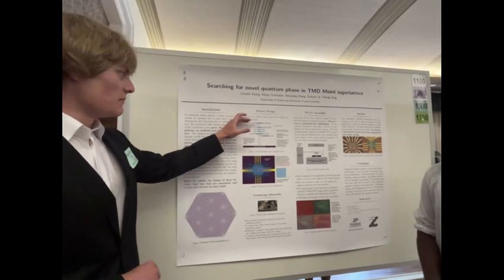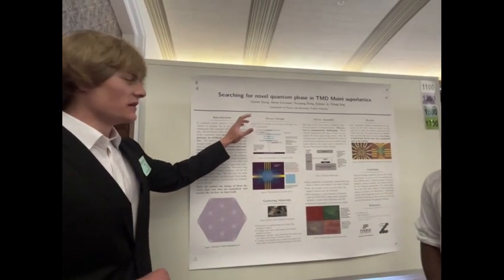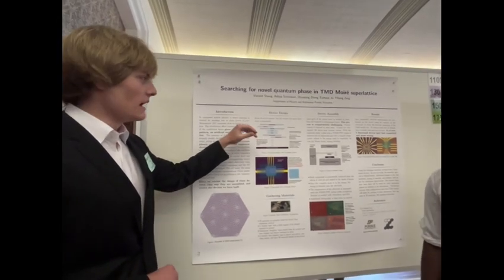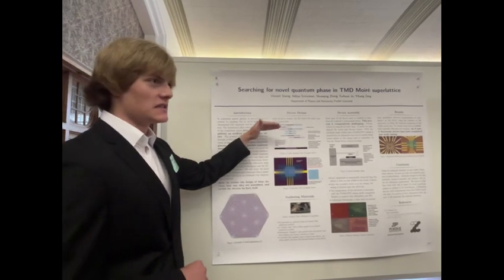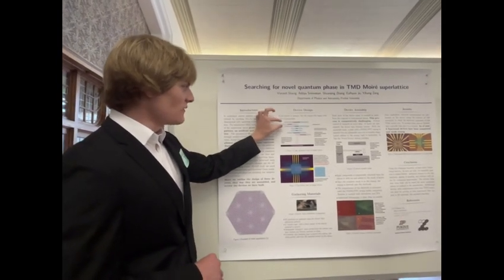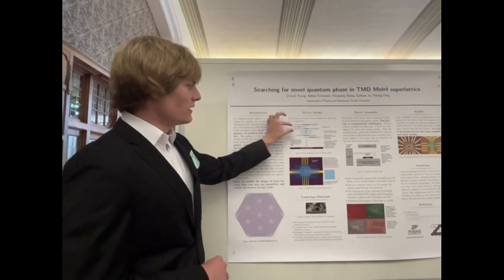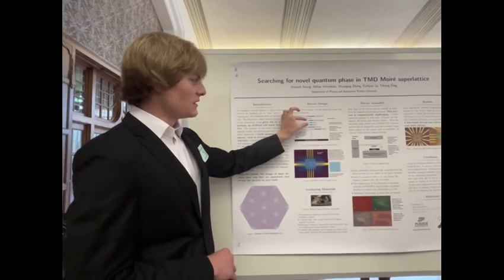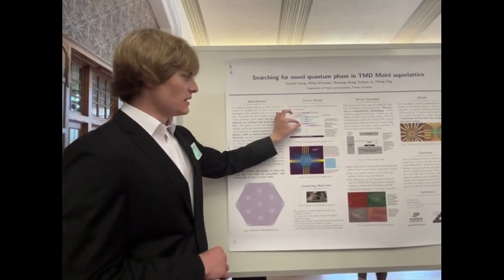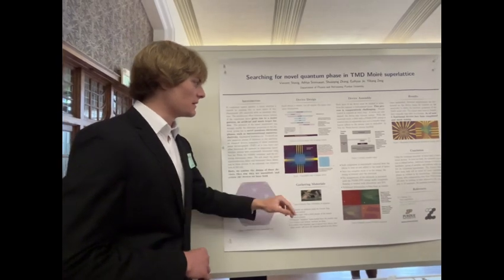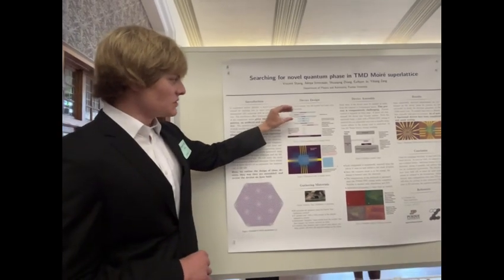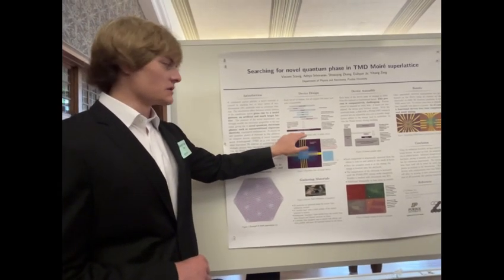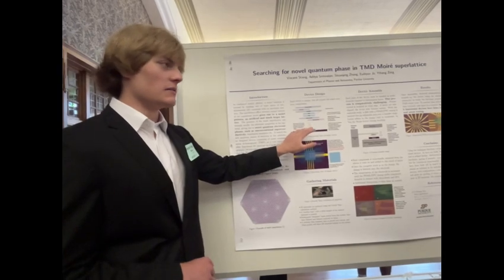So you start with this topmost HBN, that's hexagonal boron nitride, and it basically acts as a sealant over everything else, as a protective layer. And you'll see in assembly, but it also helps assemble the device. Then you have a top gate. This is made out of graphite. Then the top BN, another protective layer, and also serves as an insulating layer. This Moiré core, which is what we're interested in, bottom BN, and then a bottom graphite, bottom BN. And then all of these are stacked onto each other and lowered onto a pre-patterned electrode, which is made of silicon or SiO2 with platinum or palladium contacts.